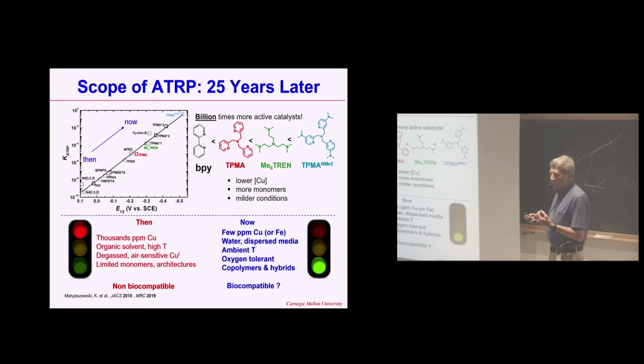So how can you evaluate this catalyst? This is in fact a very, I would say, unusually accurate correlation between the ATRP equilibrium constant, or the fraction of radicals which you generate, versus the electrochemical potential of this catalyst. And in electrochemistry, 59 millivolts is 1 order of magnitude, or 1 decade of the values of the activity. So this spans, as you could see here, approximately 600 millivolts, so it is 10 orders of magnitude.